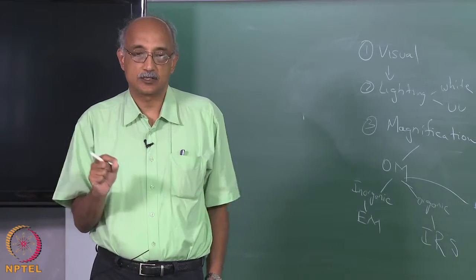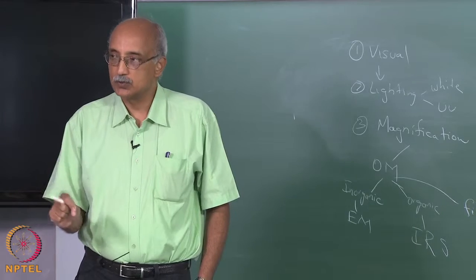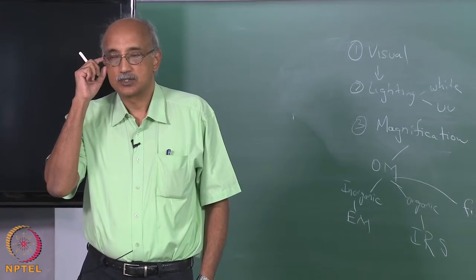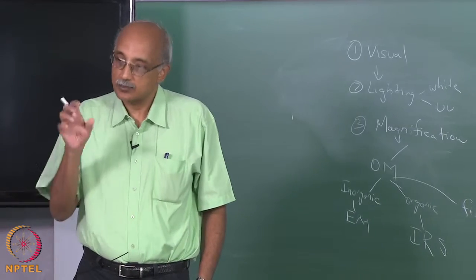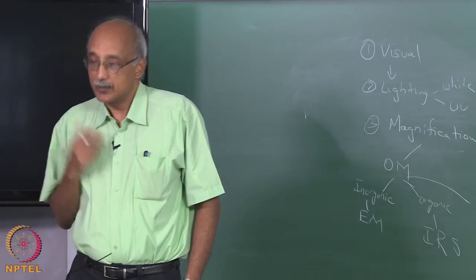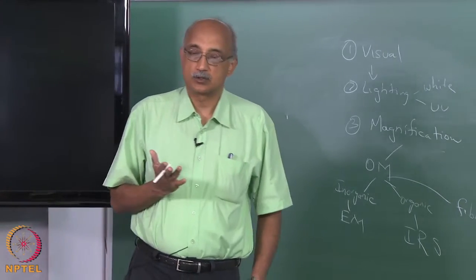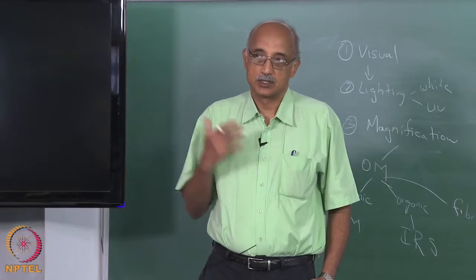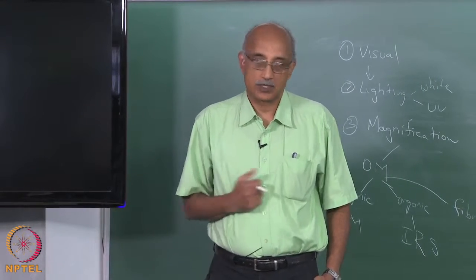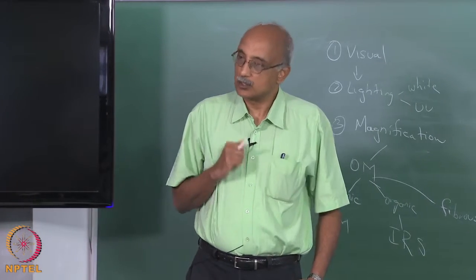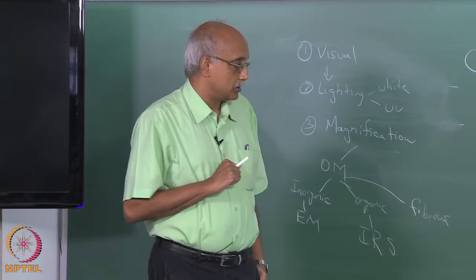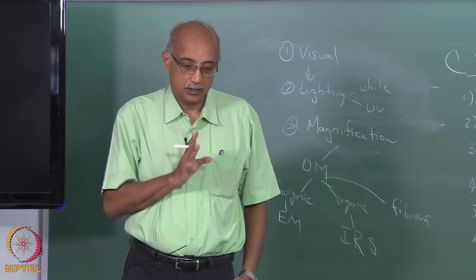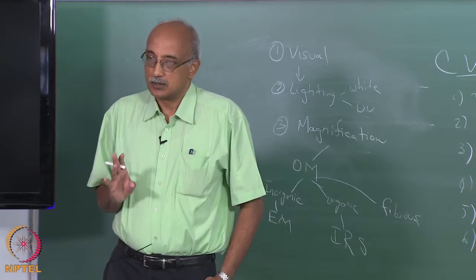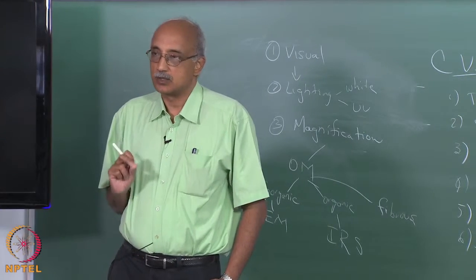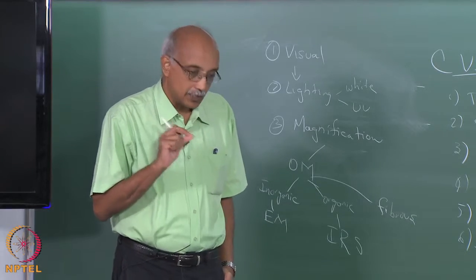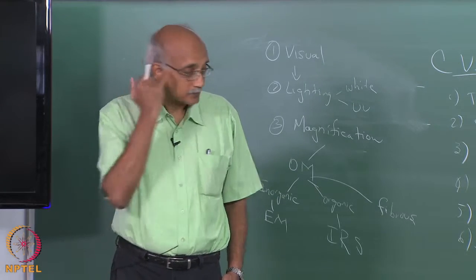So you can tell whether silicon is present as Si itself or SiO2, or Si3N4, right? So instead of just knowing that Si and N are present, you know that they are present in the form of Si3N4. Obviously, when you're making CVD films, that's very important. You don't just need to know whether the elements are present, you need to know whether they are present in a particular stoichiometry. And so ESCA is a workhorse, particularly in the CVD industry. And in fact, as far as chemical speciation information is concerned, this is probably the only technique that works very well, although certain types of materials can be analyzed by other means.